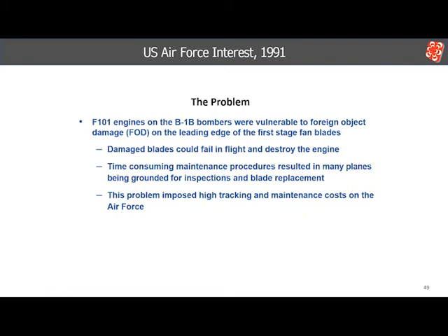It was possible that the engines were sucking in fine particles from the runways on takeoffs and landings, since most of the damage were small nicks a few tenths of a millimeter deep. These small nicks could not be tolerated. During inspections, they were detected by dragging a thread or thumbnail along the leading edge. If a nick was detected, the blade had to be replaced. Though small, they imposed a huge operational cost for damage detection and blade replacement, as well as grounding the planes waiting to be repaired.